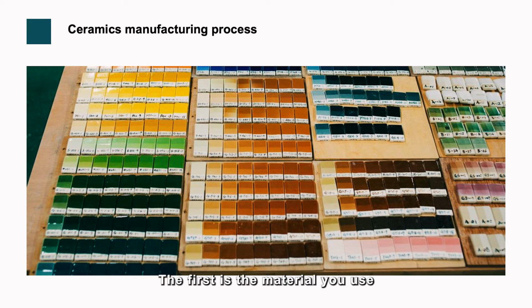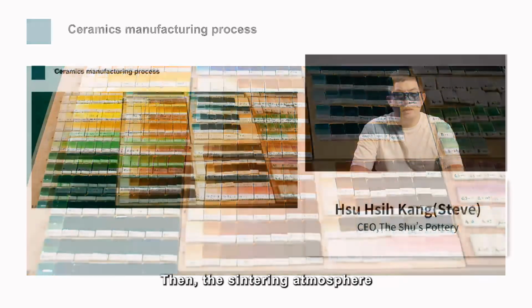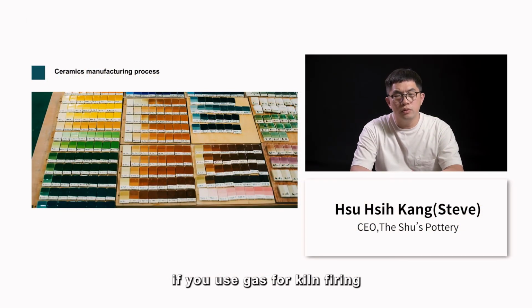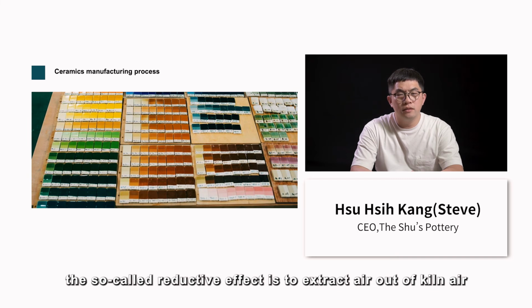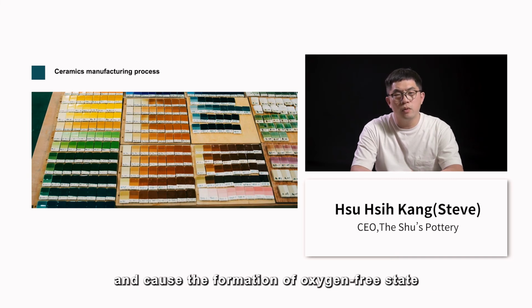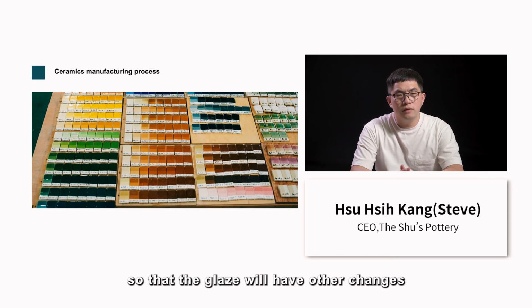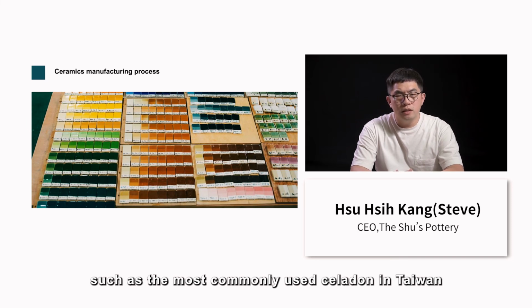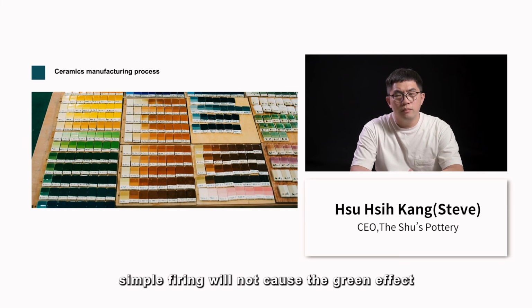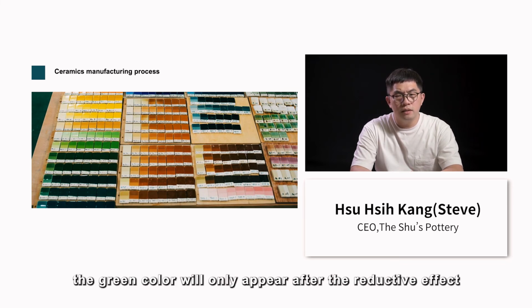The first is the material you use, whether it is clay, semi-porcelain clay or porcelain, and then the second will be related to your firing temperature. Firing temperature will affect the result. Then, the sintering atmosphere. If you use gas for kiln firing, you can make more reductive effect. The so-called reductive effect is to extract air out of the kiln and cause the formation of an oxygen-free state, so that the glaze will have other changes, such as the most commonly used celadon in Taiwan, which is made by mixing iron oxide in the glaze. Simple firing will not cause the green effect. The green color will only appear after the reductive effect.